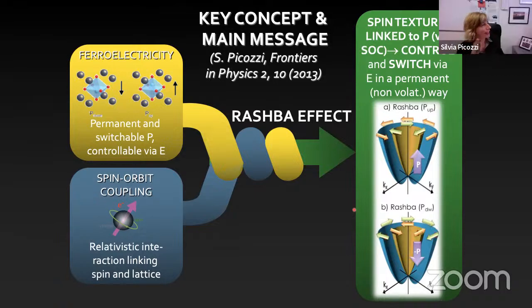Yeah. So no, you can have, okay. So let's say in a ferroelectric material, you have a polar system, which means that you have a polar group, right? And so you basically have Rashba. Still, you can have Dresselhaus. So Dresselhaus is something that you can have, for example, even if you break inversion symmetry, but without having a polar axis. So, for example, if you have zinc blende, you have Dresselhaus, but it's non-polar. So you can have a sort of spin splitting there, but you cannot really get this net spin polarization. I mean, we can. I don't have slides to. Yeah, maybe we can discuss that later.